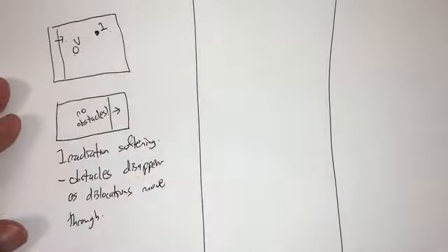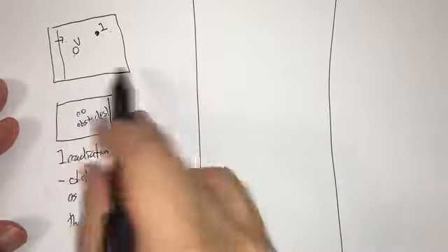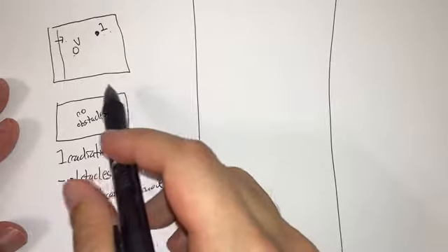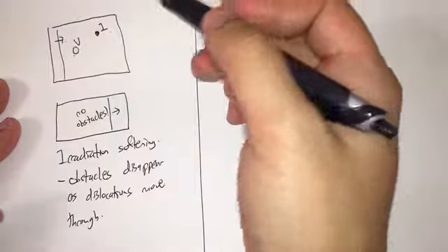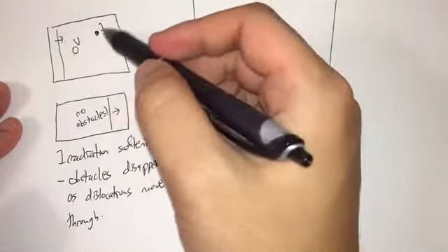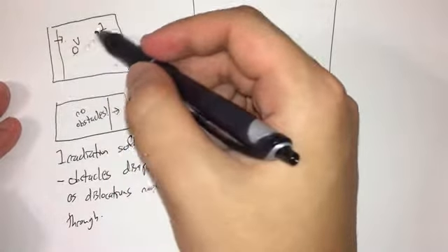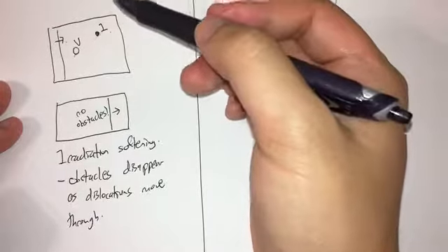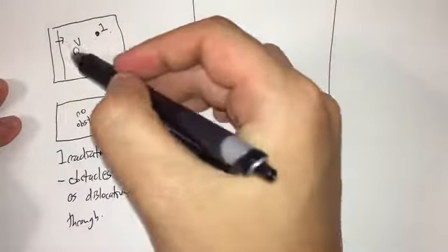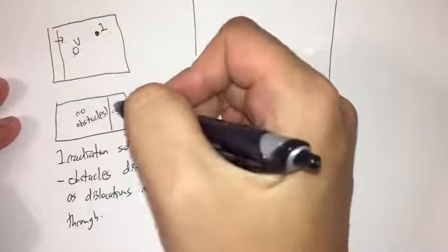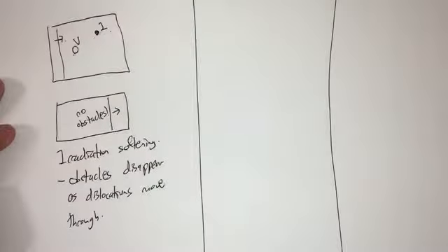So when dislocations are moving through this irradiated sample, it's not really that radiation directly causes a softening effect, but rather it's because radiation leaves behind all these vacancies and interstitials and similar defects, and these defects can be cleaned up by this dislocation movement.